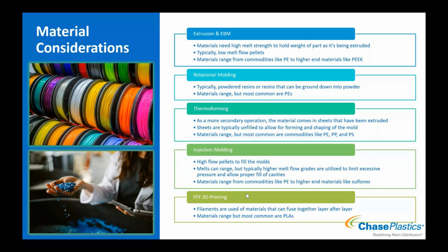So when you're extruding it down, or extruding it to the side, so down for your extrusion blow molding, you saw in the picture it's extruding down. Other extrusion processes, it's extruding typically out, so more horizontal. It has to be able to hold its own weight. If you go to extrude it out and it doesn't have any strength there, it's just going to break apart, and then you can't have a continuous process if it's breaking. So these materials will have to have high melt strength.